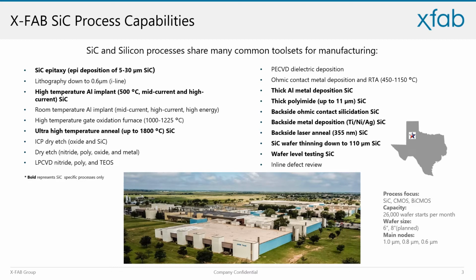Silicon carbide and silicon processes share many common tool sets for manufacturing. But there is also a lot of silicon carbide specific processing steps and tools necessary to manufacture both in parallel. In the past, we added capabilities for silicon carbide epitaxy in-house, added several high temperature implants and annealing tools, both very critical process steps for the silicon carbide MOSFET. We offer thick metal deposition with a polyimide cap, backside ohmic metal and wafer thinning down to 110 micrometer.